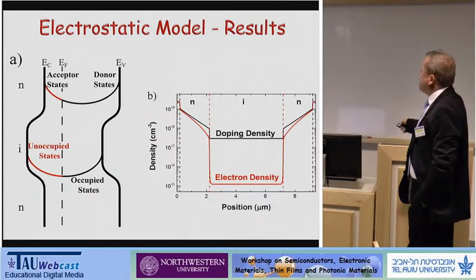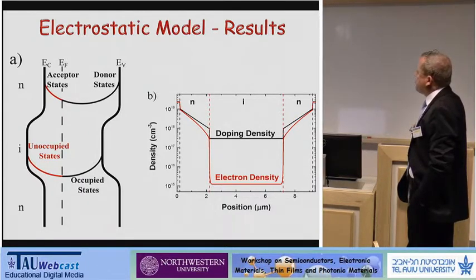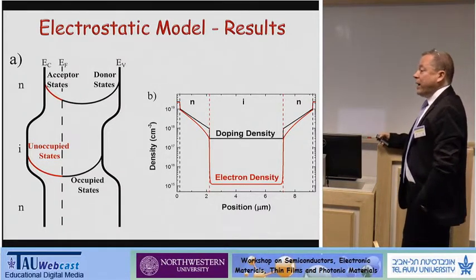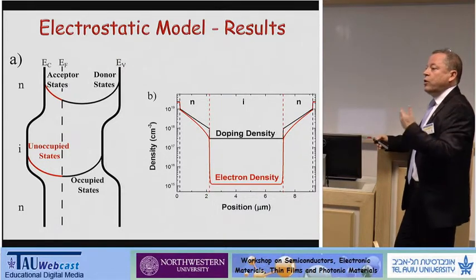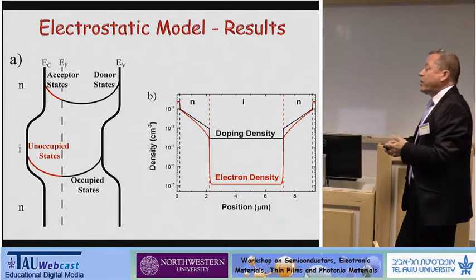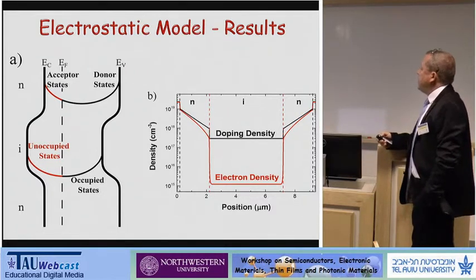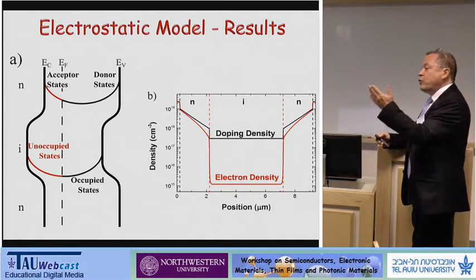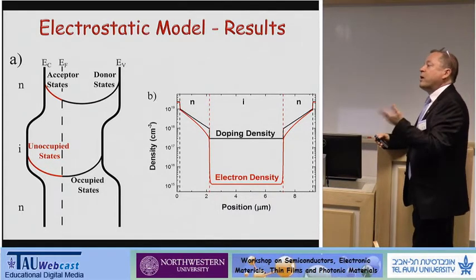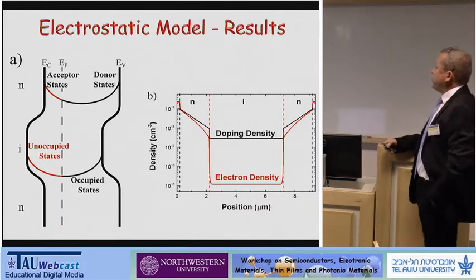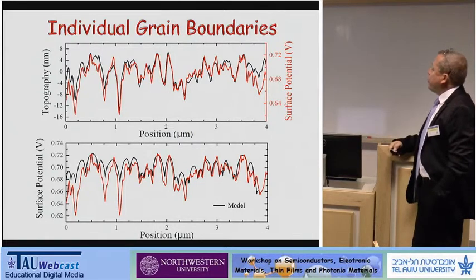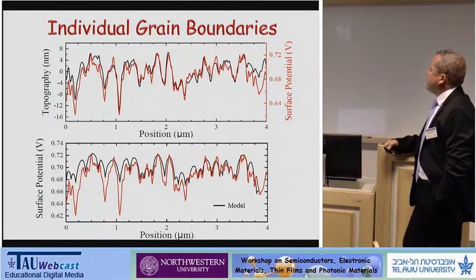Another important fact here is that, because of the carrier trapping in the boundaries, you have a very large difference between the doping density and the free electron density, because inside the grains, the electrons are trapped at the grain boundaries, and they reduce the carrier density by almost more than 2 orders of magnitude. So one important message here: if you want to have good electrical devices based on polysilicon nanowires, you need to have the dopant density above 10 to the 19. So you need the dopant density to be higher than the grain boundary interface state density in order to have good electrical properties.